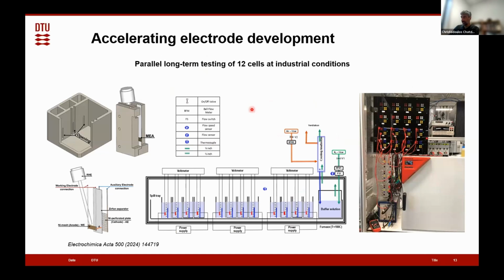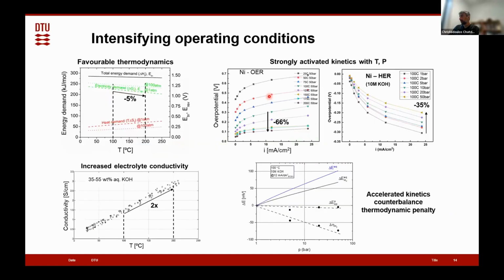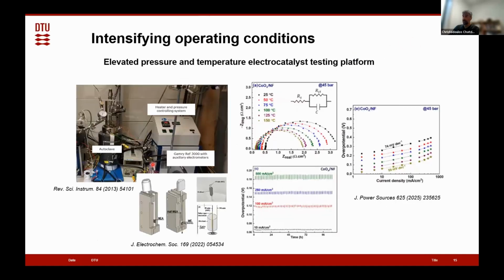We also try to accelerate electrode development and understanding of degradation through parallelizing testing with 3 electrode holders that can be run in parallel. So with relatively low cost, we can have at least 12 cells running in parallel for long periods of time. As a final word, we try to intensify operating conditions by employing custom-made autoclaves, where we can carry out electrochemistry at high temperatures and pressures. This is an example of electrodes tested up to 150 degrees Celsius at 50 bar.